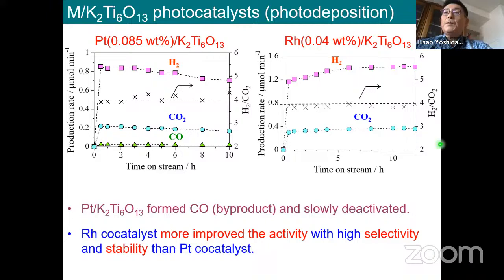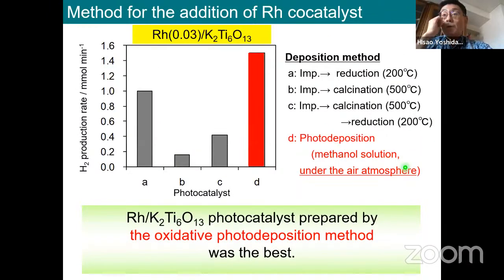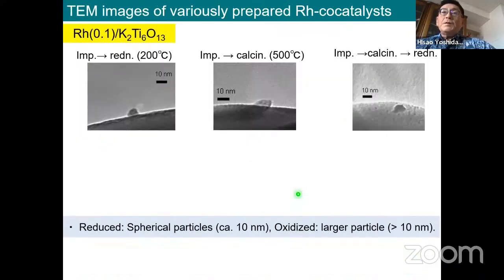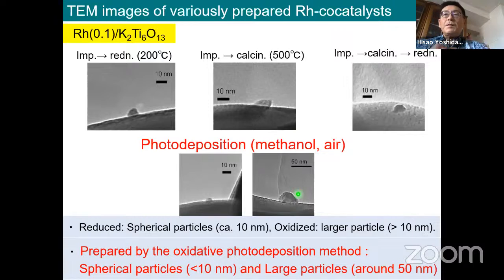Then we changed the loading method of the rhodium on potassium titanate. In this case, we found photo deposition is quite effective for this reaction. And we observed the surface by using microscopy. We found some species of rhodium, and in the good sample, we found 2 types of co-catalysts loaded on the surface. The size is quite different, and the morphology is also different.